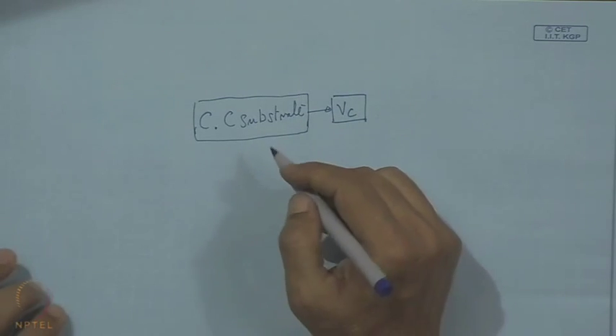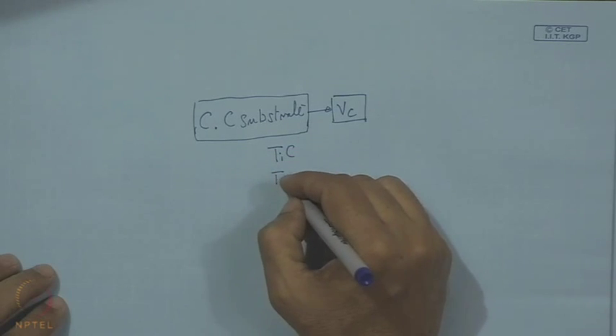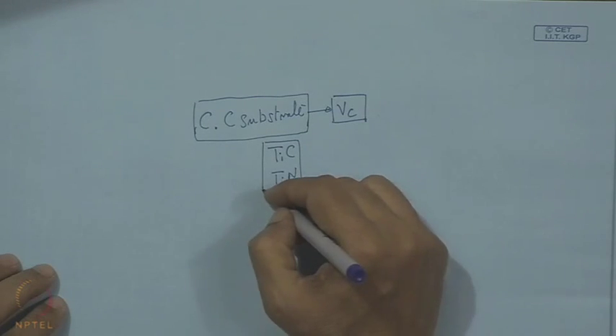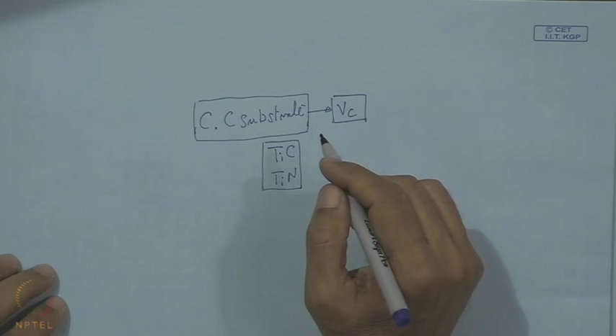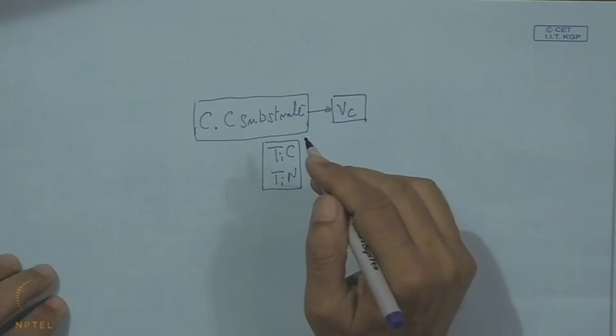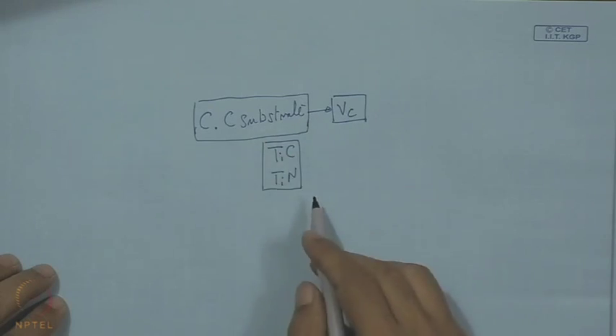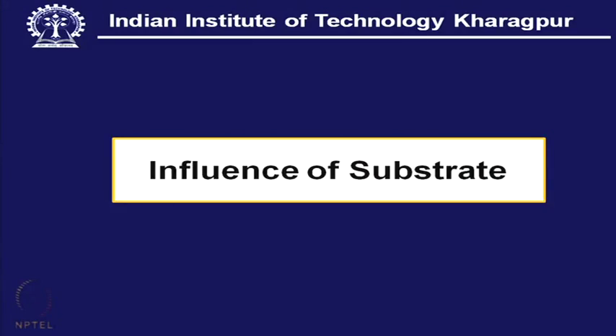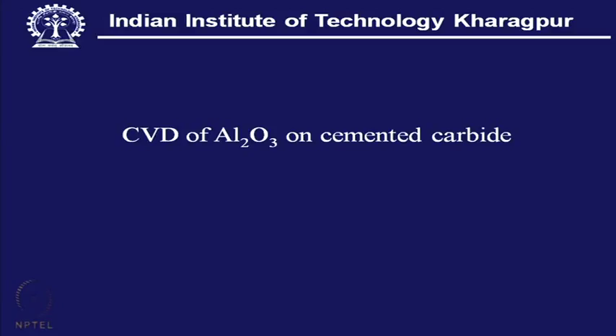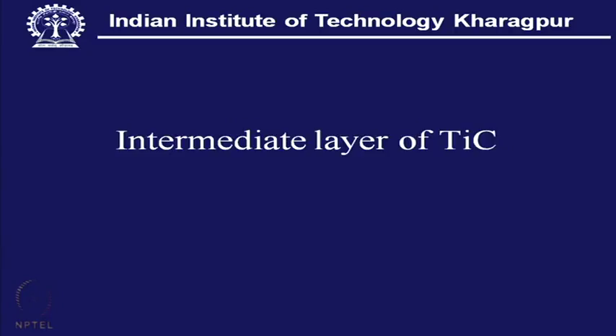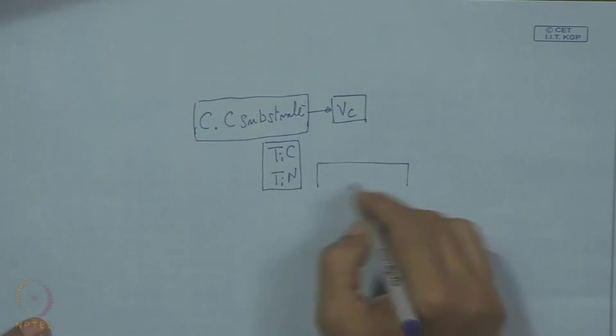Now, this cemented carbide substrate is a very successful substrate when it is TiC or TiN. For that, this is a very good candidate, but when it comes to deposition of aluminium oxide on this cemented carbide substrate, we find a lot of difficulties. Now, what are those difficulties? Let us look into detail. So, it is actually CVD of aluminium oxide on this cemented carbide substrate. Now, before we go to this intermediate layer, let us try to understand the basic problem with this cemented carbide.